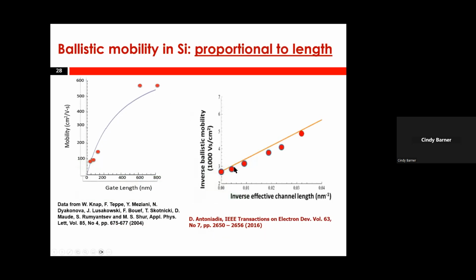In 2016, there was a much better paper from MIT. You see this beautiful, nearly linear trend. So mobility indeed decreases. So we now understand that we should take care of the contacts even more in a short channel device. And we also understand one point that is extremely important. Since this is the dominant mechanism of scattering, then conventional scattering mechanisms play smaller role. And that's one of the reasons why the idea to replace silicon with gallium arsenide in VLSI basically failed. Because once you start scaling to 20 nanometers or so, it doesn't really matter that gallium arsenide is much more conductive. Mobility is about 10 times larger in longer samples, like 1 micron, or 2 micron samples, or 1 millimeter samples, whatever. You go to 20 nanometers, and this advantage is really diminished.